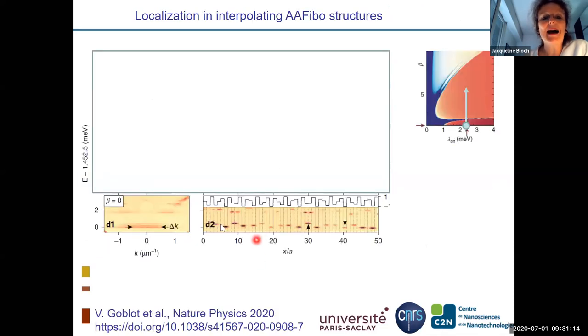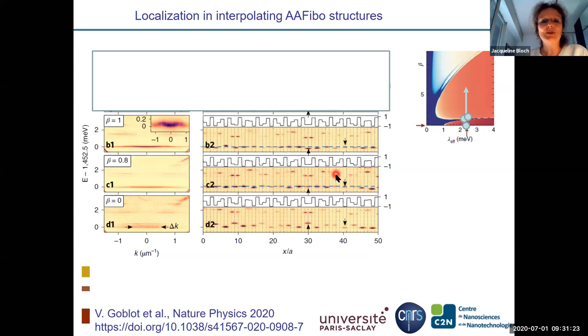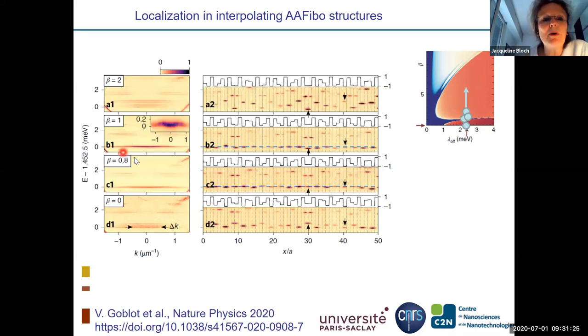Now we are here in the phase diagram, and I am going to show you different points when going up in beta. Here you see two points close to the transition. All these points, which were scattered, come very close to each other, hybridize, and form something that looks very flat. Then when you go above these values of beta, you again recover very scattered localized spots.